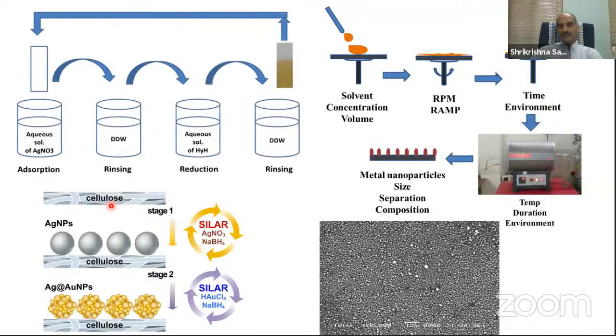We immerse it in the solution of the metal ions, where these metal ions will adsorb, and we rinse to remove all the loosely bound species. Then we put it in the reducing agent solution, in this case, for example, hydrazine hydrate or sodium borohydride, or whatever is suitable. Then we rinse it again, and we see that these silver nanoparticles grow on the substrate. The substrate, as I already told you, can be glass, paper, cotton, or anything. And it's not only silver, you can grow silver, gold, and so on and so forth. I will show you some of the results.